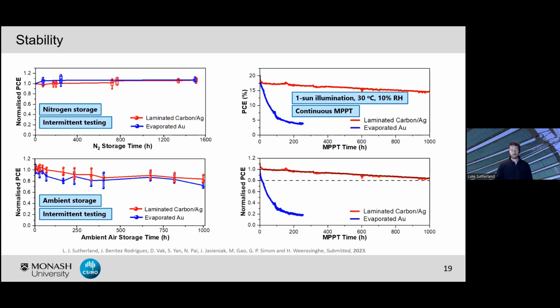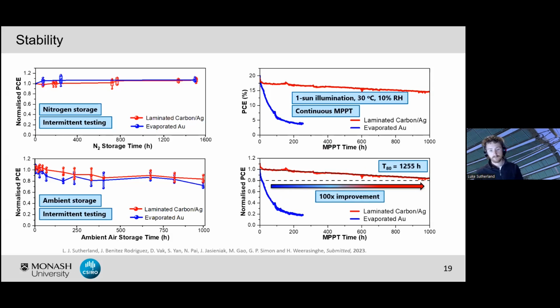If we normalize this, taking into account the consensus that was published in 2020, looking at the stabilized efficiency, we're able to calculate the T80 lifetime of these cells of just over 1,200 hours. So these are unencapsulated devices as well, which is a 100 times improvement. So 2 orders of magnitude improvement comparing our evaporated gold to the laminated carbon and silver electrode.